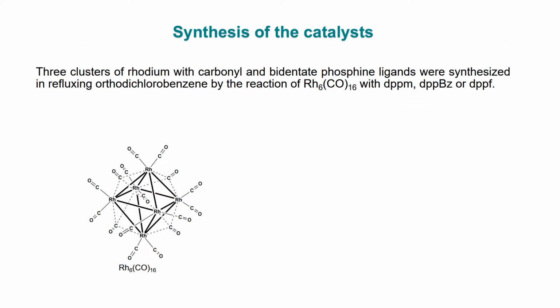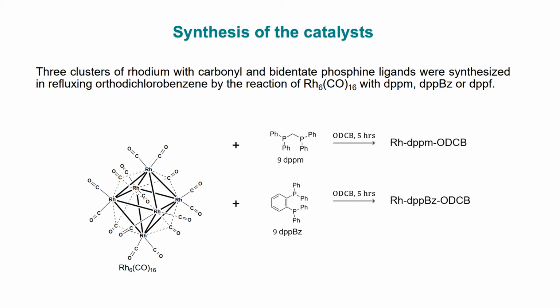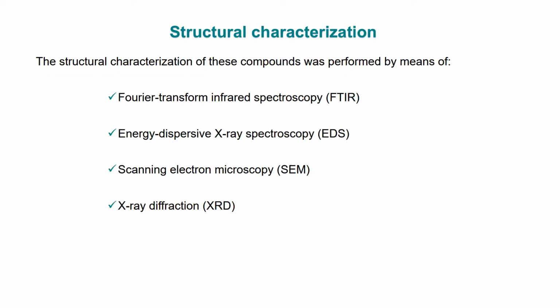Synthesis of the catalysts. Three clusters of rhodium with carbonyl and bidentate phosphine ligands were synthesized in refluxing ortho-dichlorobenzene by the reaction of hexadecacarbonylhexarhodium with methylenebis(diphenylphosphine), o-phenylenebis(diphenylphosphine) or ferrocenylbis(diphenylphosphine). The structural characterization of these compounds was performed by means of Fourier transform infrared spectroscopy, energy dispersive X-ray spectroscopy, scanning electron microscopy, and X-ray diffraction.